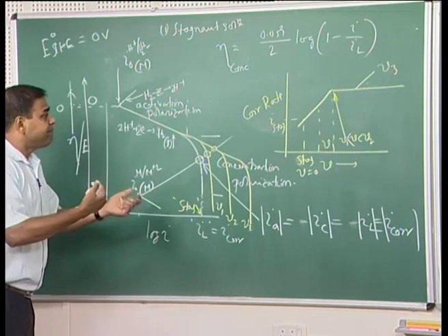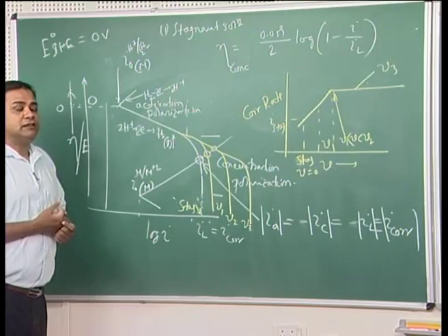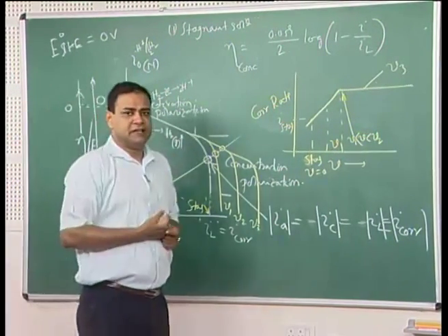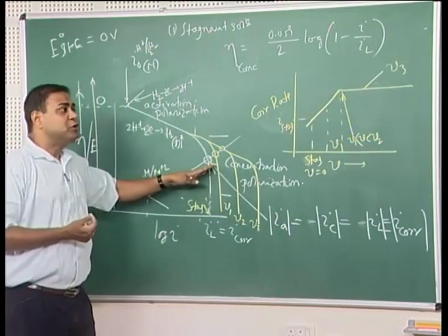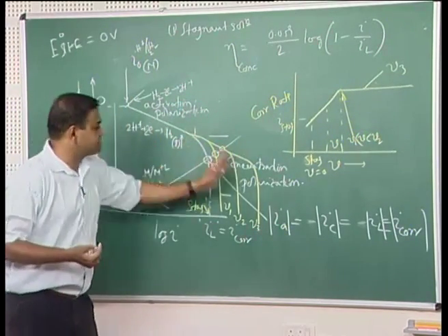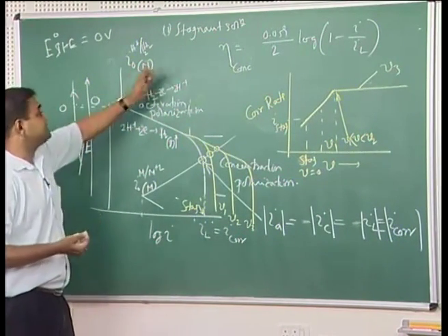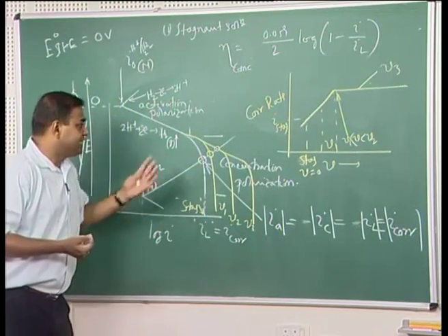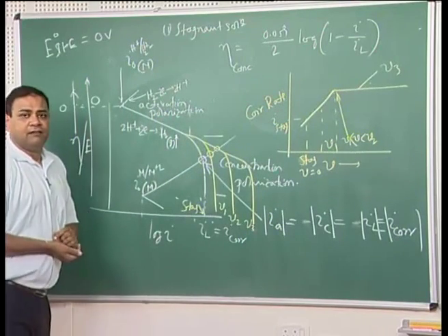So we have that notion that if we increase the velocity for an active metal, then there is a possibility that the corrosion rate would always increase. But it does not happen like this. Of course, there would be increase, but once you have this particular situation, because of concentration polarization effect from the cathodic side, then you are going to have a plot like this, fine.